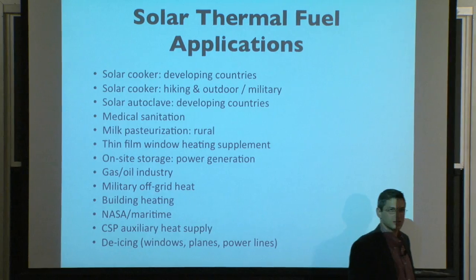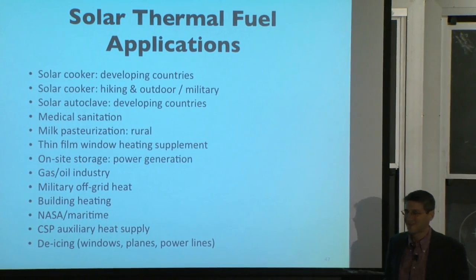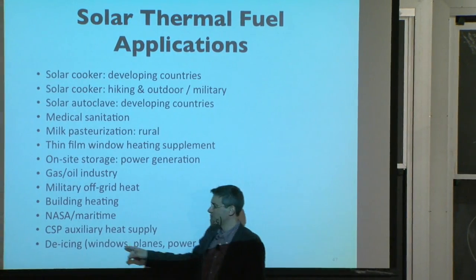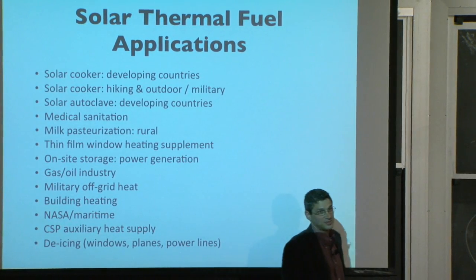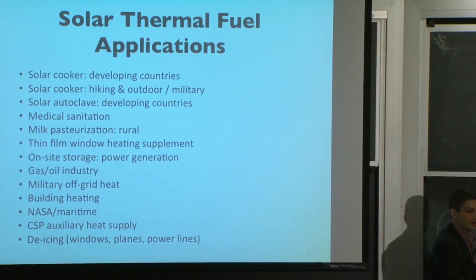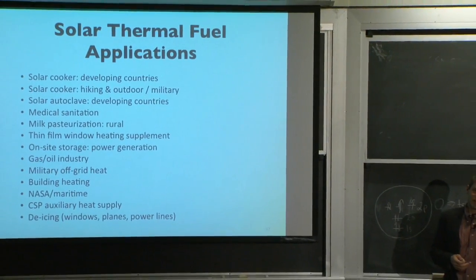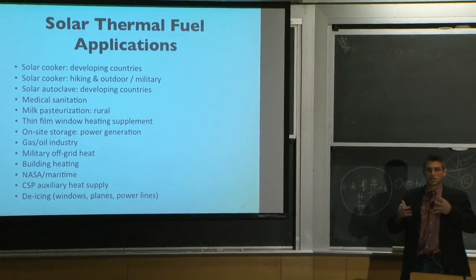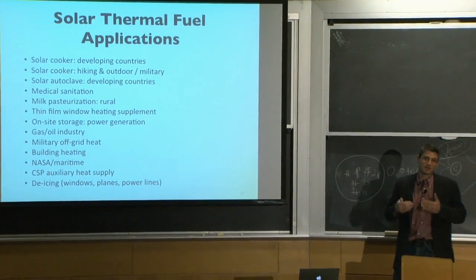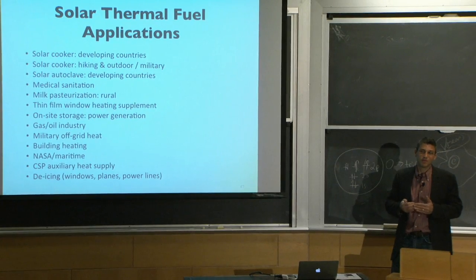And Sam can, with our solar fuels, when they're made, he'll be able to de-ice a window for you in about 5 seconds, right? And that's pretty cool. So you can embed this stuff inside of glass and have it passively absorb the sun's energy during the day. In the morning, trigger it, and it gives you 300 Celsius inside the glass, right? You don't need to melt much ice to get it to fall off, right?